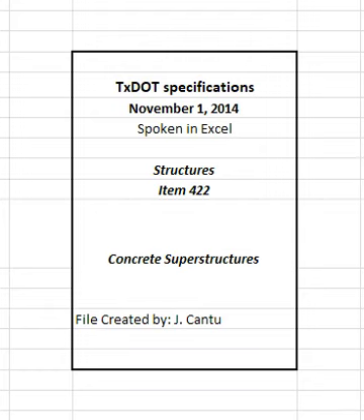Adequately illuminate the entire placement site when mixing, placing, and finishing concrete in non-daylight hours as approved. Furnish adequate shelter to protect the concrete against damage from rainfall or from freezing temperatures as outlined in this item if changes in weather conditions require protective measures after work starts. Continue operations during rainfall only if approved. Use protective coverings for the material stockpiles. Cover aggregate stockpiles only to the extent necessary to control the moisture conditions in the aggregates. Allow at least one curing day after the concrete has achieved initial set before placing strain on projecting reinforcement to prevent damage to the concrete.